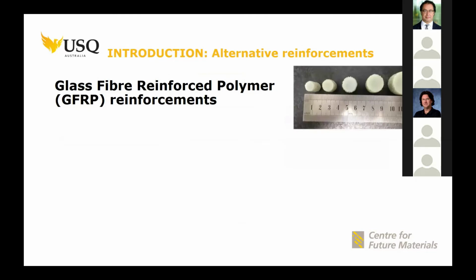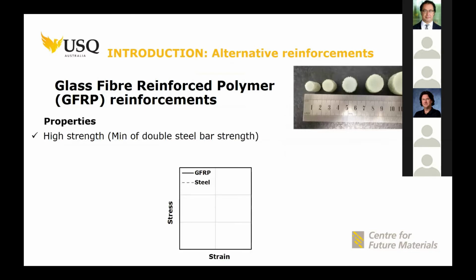All of us know that the newly manufactured glass fiber reinforced polymer reinforcement is now globally accepted as internal reinforcement for concrete structures. And you can tell from the properties that it has high strength compared to the steel. You can see from the figure here the difference in strength, at least double. And despite the low modulus of elasticity, it actually has high strain capacity. It's at least 1.5 times the rupture strain, not the yield strain, but the rupture strain of the steel bars. All of this depends on the grade of the glass fiber bars and the steel bars. There is also a high stiffness to weight ratio for the GFRP bars compared to the steel bars. It's around 0.25, or a quarter of steel density.